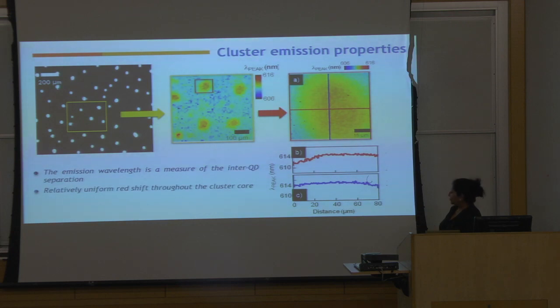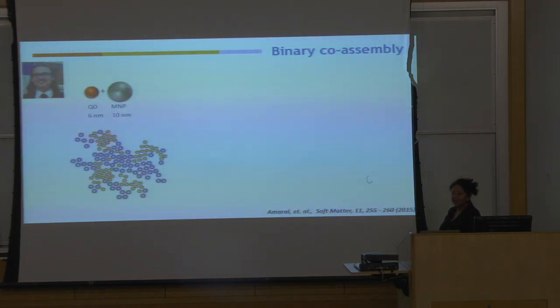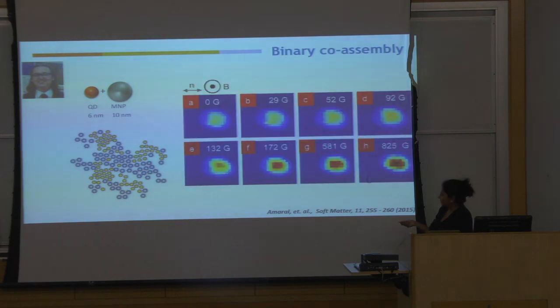After this experiment, we made clusters with one kind. The next step is you make clusters of 2 kinds. So you put 2 things together. This effort was led by UC, who's here. Both Andrea and UC have since graduated. We put quantum dots and magnetic nanoparticles in the liquid crystal, did the same procedure, cooled them down, and made them form clusters. We did X-ray scattering to make sure that the particles were actually in the same cluster. And then we put them in our cryostats.